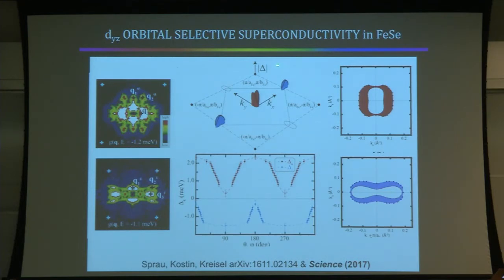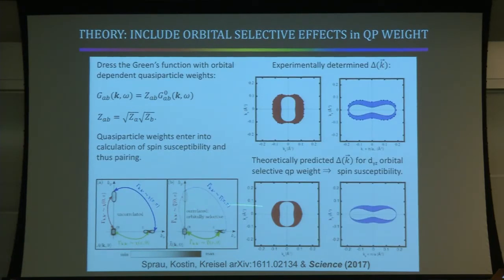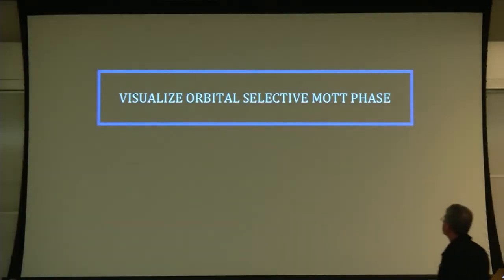That's great. There's a lot of skepticism about this because in order to get this correspondence, you have a sequence of arbitrary numbers, right? You adjust the quasi-particle weight for dxy to a tiny value, for dzx to an intermediate value, and for dyz near 1. So the question is, where do these numbers come from? One answer to that would be a DMFT calculation, which people are doing but have not done. But another answer would be to do another experiment where you measure those numbers independently and find out, does it make sense empirically? So here's the other experiment.